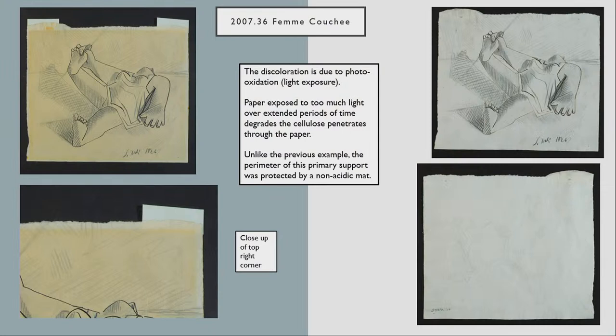In here, we have the opposite problem. The discoloration here is due to photooxidation, or in other words, light damage, over light exposure, or overly high light exposure. The paper exposed to too much light, over an extended period of time, degrades the cellulose and penetrates through the fiber. So if you look at the close-up on the bottom, you see where there's a little white perimeter. If this were mat burn, the discoloration would be like the one before. The perimeter would be stained and the main image would be lighter. But here it's the opposite. The mat in this case was archival, protecting the perimeter, but it was exposed to too much light, so it oxidized because of light. And then here's the result on the right after treatment.